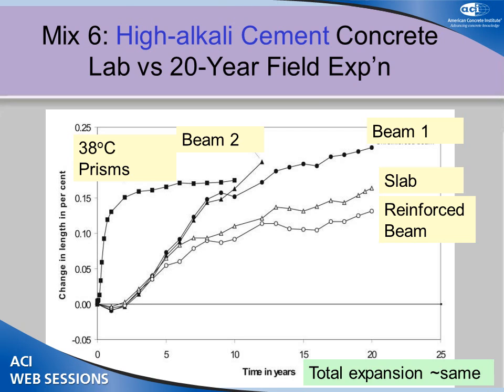And even though we don't get 38-degree weather in Ontario, it eventually gets there in the concrete. The surfaces do get that hot due to solar reflectance. You can certainly get 40 and 50 degrees under the surface of concretes in the summer there. But then we get freezing weather as well. I'm sure these would go much faster over in southern climates. But it's interesting to compare the net expansion after a long period of time, just different rates.